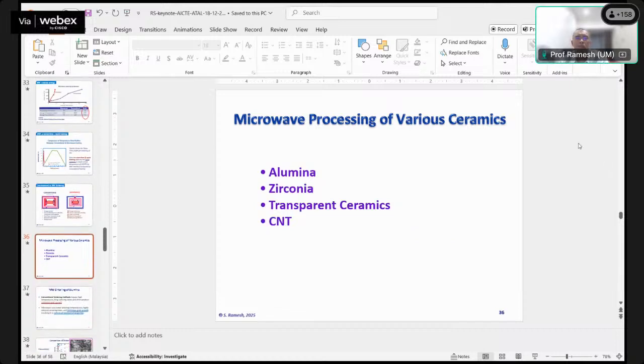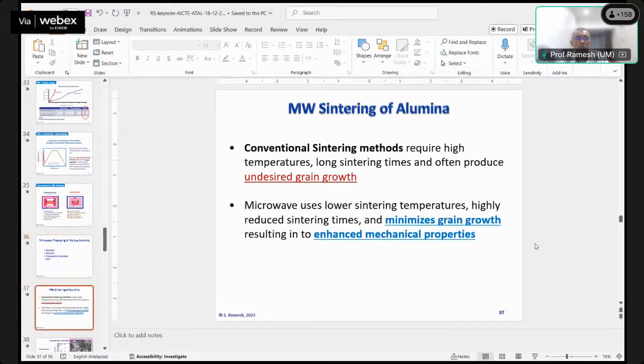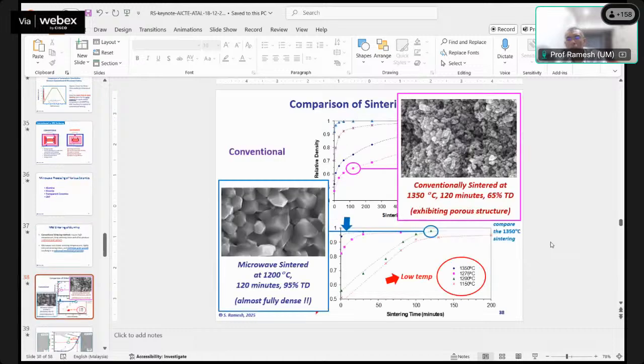Some examples of processing with microwave. Alumina: one of the things with alumina, as you know, is that it needs to be sintered at high temperature for a very long period of time. As a result, you have grain coarsening. When the grain gets bigger, you lose the mechanical strength. So this is the issue, and the challenge with sintering of alumina is really to minimize grain growth so that you have higher mechanical properties.